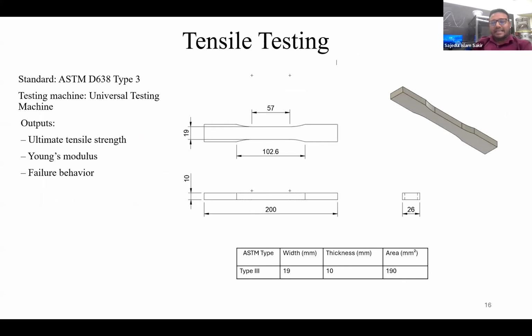Now I am going through the tensile testing, what I am currently doing. Our lab has chosen the ASTM D638 Type 3, as the printer nozzle diameter is high, so we have to use this Type 3 sample. So what we will do now, I'm doing it actually now.